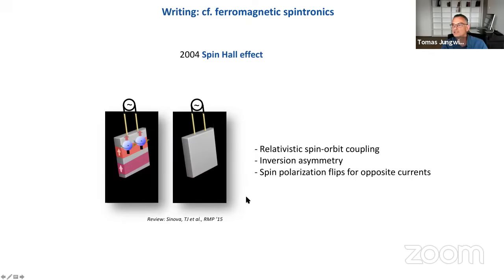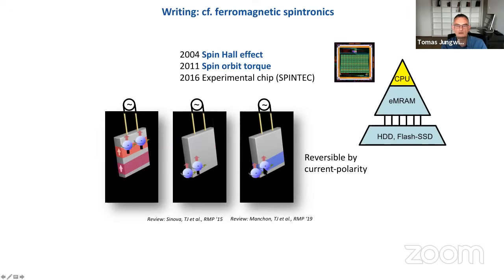We live now in the 21st century, where we have discovered an alternative means how to switch magnets. It started from recognizing that even by taking a non-magnetic material, we can generate non-equilibrium spin polarizations just due to the relativistic spin-orbit coupling, and we will get spin accumulation wherever or whenever there is inversion symmetry breaking. Now, if we combine this effect with a magnetic order in equilibrium, so if we get these non-equilibrium spins in contact with a magnet, a ferromagnet in this case, we can also induce current-induced switching.